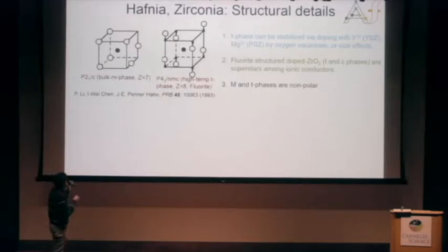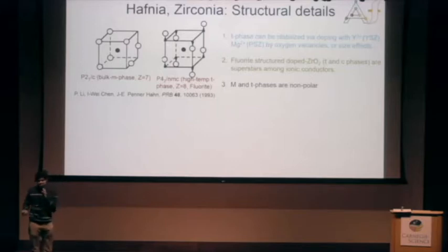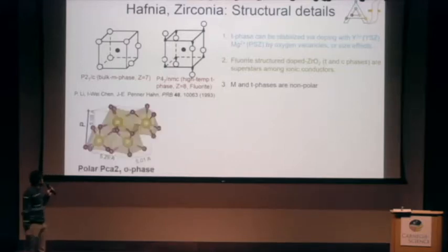And the more well-known phase is the T phase, which is the high temperature and high pressure phase. However, this T phase could be stabilized by doping hafnium or zirconium with yttrium or magnesium, and these yttria stabilized zirconia and magnesia stabilized zirconia are blockbuster materials for solid ion conductors. So these are very well studied. However, the problem with these two phases is both of them are nonpolar. So both of them are useless for ferroelectric applications.